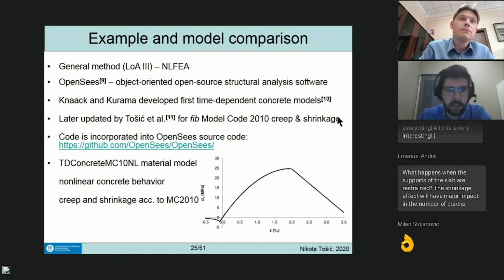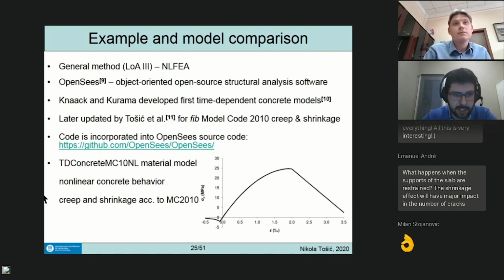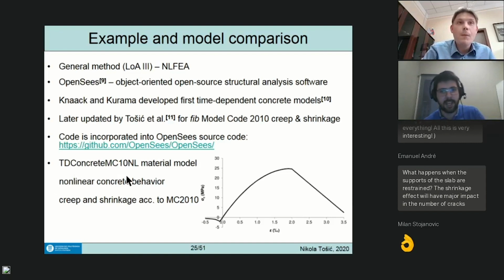And within them, we have this TD concrete, like time-dependent concrete, MC10, standing for model code 2010, NL, nonlinear material model. So as I said, with the nonlinear concrete behavior, which is given here with parameters, inputs that can modify this curve completely in compression and in tension, and give you creep and shrinkage according to model code 2010.